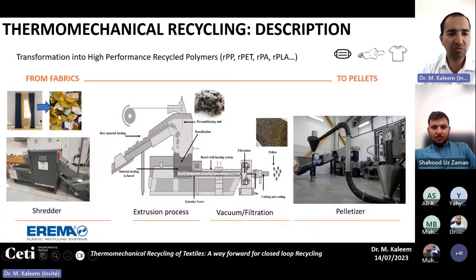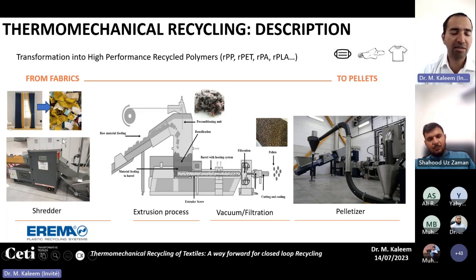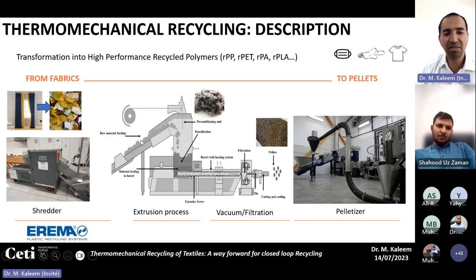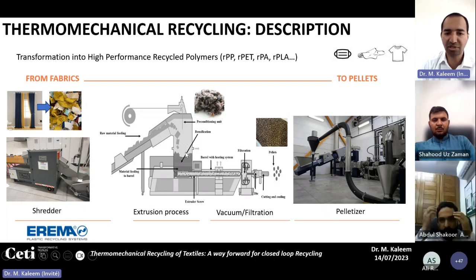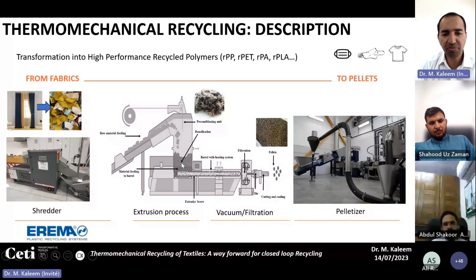When the material is well sorted, for example, I can give you an example from trials that we have done at CETI. One of the customers gave us window curtains, and first we have to shred them and put them in a size that is more suitable for the thermomechanical recycling machine. So we feed it, and then we put it in the densifying unit. There you densify it. That means you further shred it and make microfibers out of it through mechanical friction.